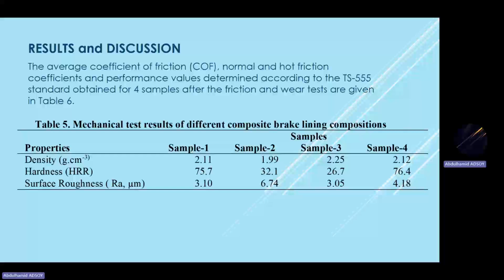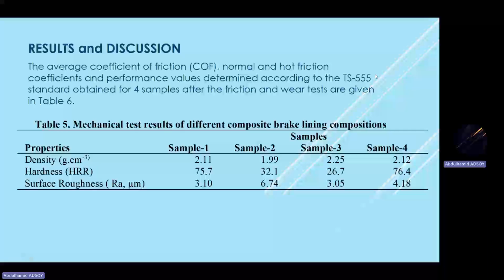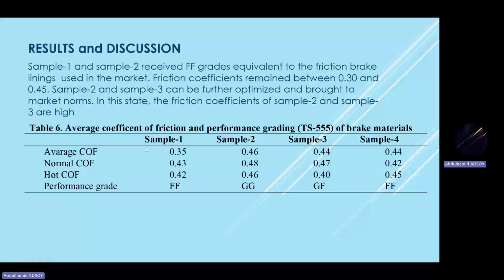You can see from here. Now, the average coefficient of friction, normal and hot friction coefficients, and performance values determined according to TS 555 standards were obtained for the 4 samples, which are shown in this table. Based on the difference between the normal and hot friction coefficients, we give a letter grade for each, based on TS 555.